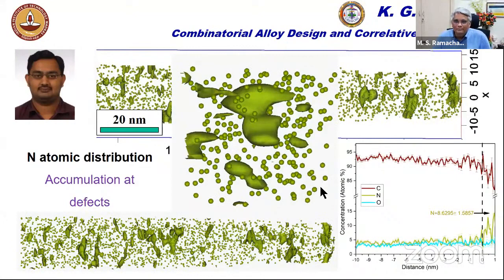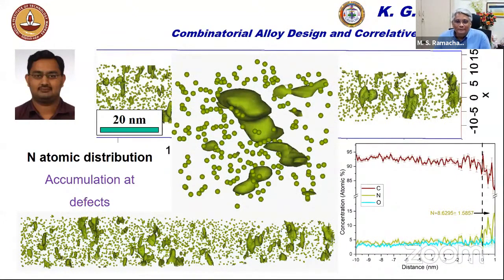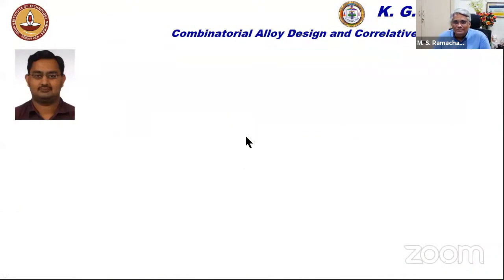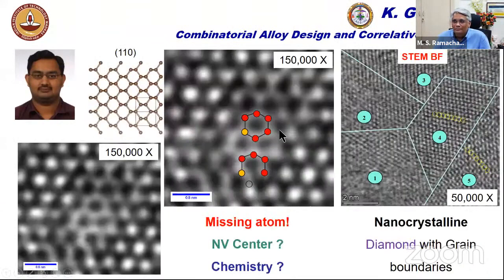Yeah, so this is so impressive. Probably the first group to have seen this, the complete hexagonal, the 110 plane and a missing atom. This is really remarkable. That's the kind of imaging technique that you need in order to understand. One is to identify what that missing atom is. That's the next step. But of course, from what I understood from Pradeep's work, we certainly have nitrogen everywhere. So the missing atom could be a nitrogen, and what you're seeing there could be an actual NV center. So it's quite exciting.